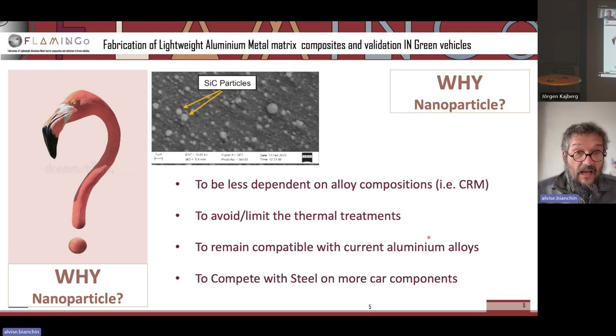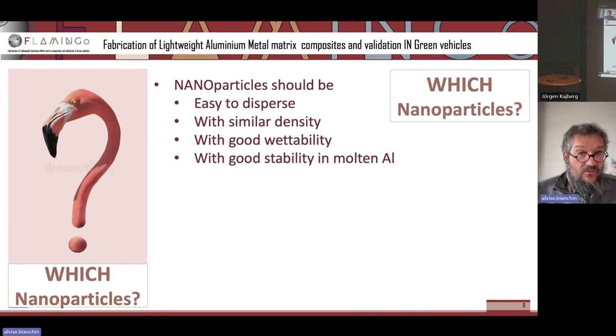So if this is quite convincing as an approach, then we need to identify which nanoparticles to use. The boundary conditions for this are that nanoparticles should be easy to disperse. They should have similar densities to the aluminum melt, good wettability in the melt, and also good stability, so not breaking up in the aluminum due to the temperatures that are present. More than that, the nanoparticles should be safe.